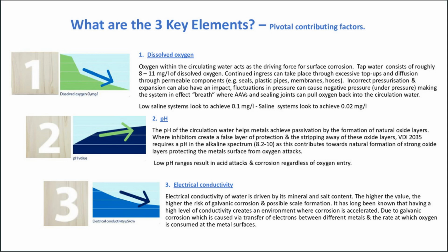Electrical conductivity. Electrical conductivity of water is driven by its mineral content and salt content. The higher the value, the higher the risk of galvanic corrosion and possible scale formation. It has long been known that having a high level of conductivity creates an environment where corrosion is accelerated due to galvanic corrosion, which is caused by a transfer of electrons between different metals and the rate at which oxygen is consumed at the metal surface.